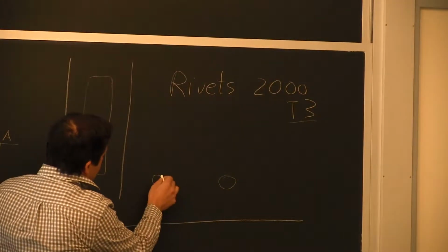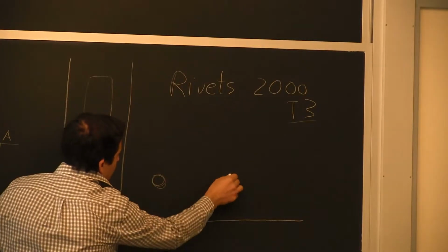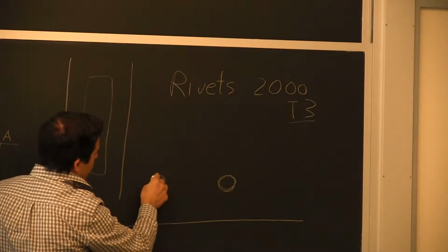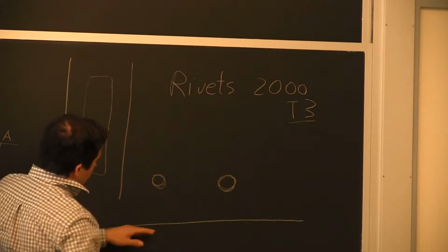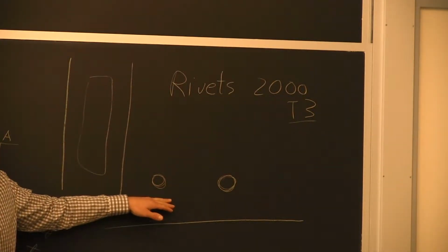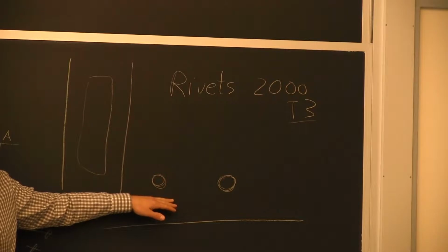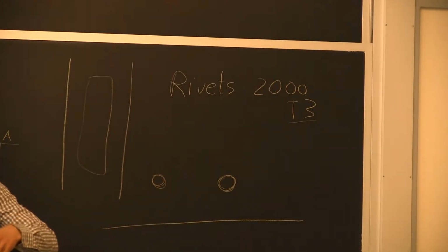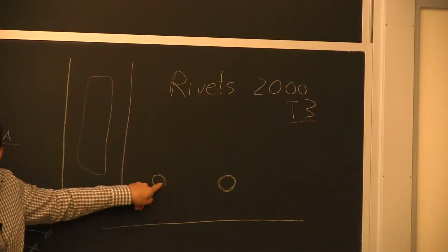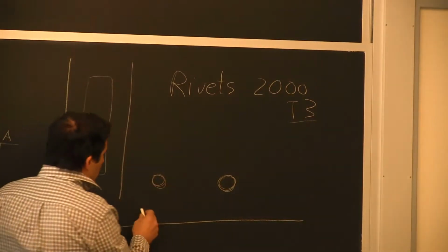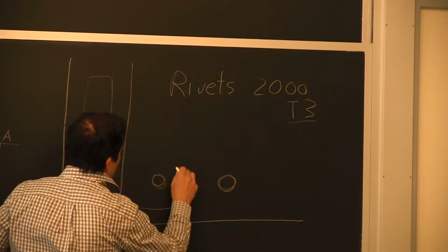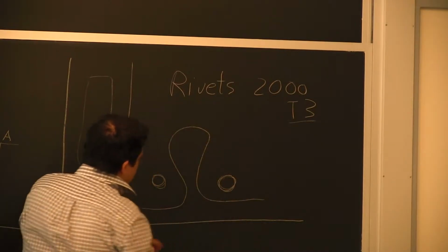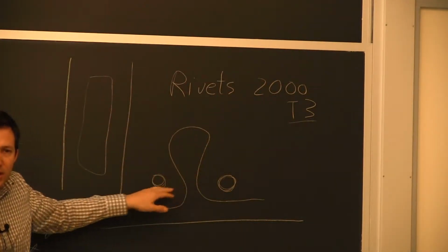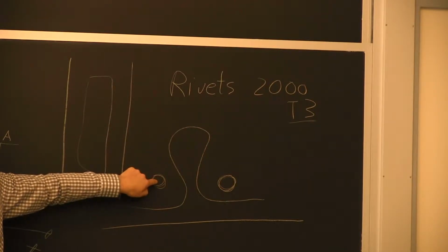If there's enough strain field, enough deformation going around the particles, the dislocation will feel it. It will realize it's coming into a zone where the crystal is not in the minimal energy configuration. It's going to be harder for the dislocation to reach the precipitate. And that's what happens when you start forming loops like this here, where the dislocation just goes right in between and it just can't get right over the precipitate.